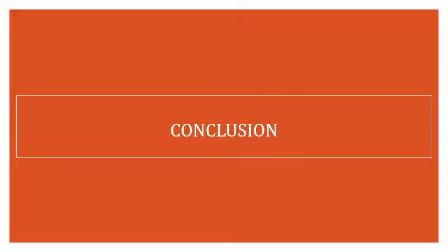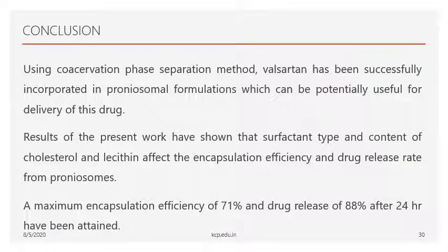Now let's move on to the conclusion. As per the conclusion of the author, they reported that by using the coacervation phase separation method, they successfully incorporated the Valsartan drug in proniosomal formulations. The evaluation tests reveal that the type of surfactant, cholesterol and lecithin affect the encapsulation, drug release and stability. The maximum encapsulation is only 71% and drug release is 88%.